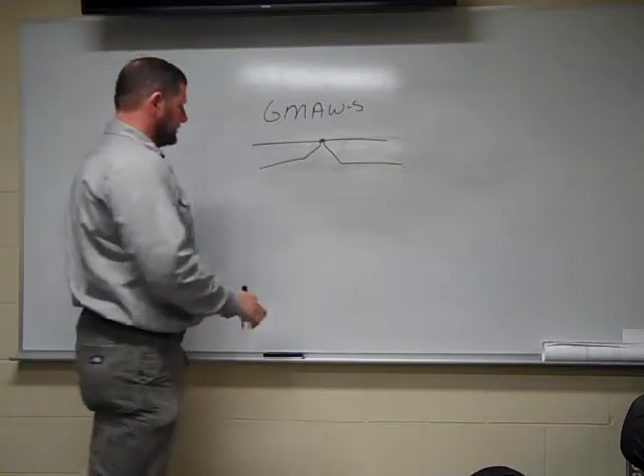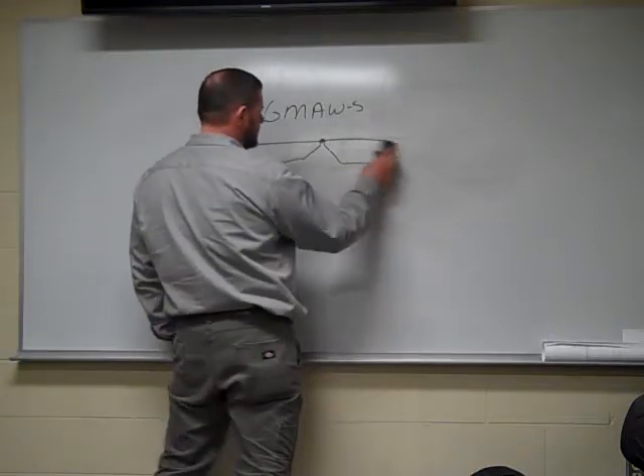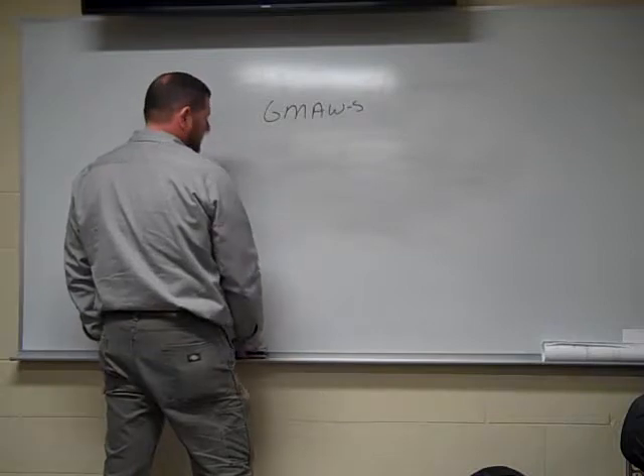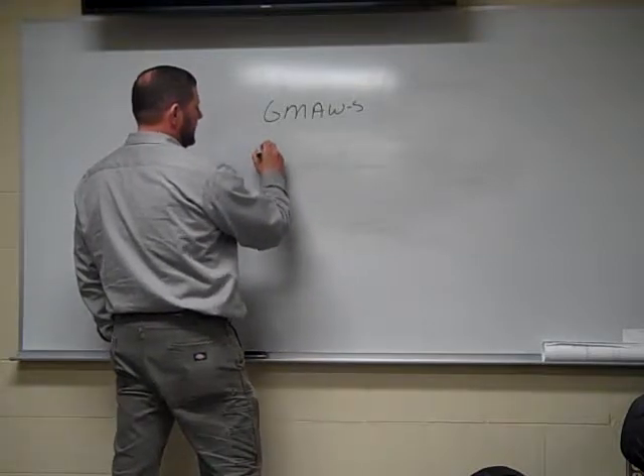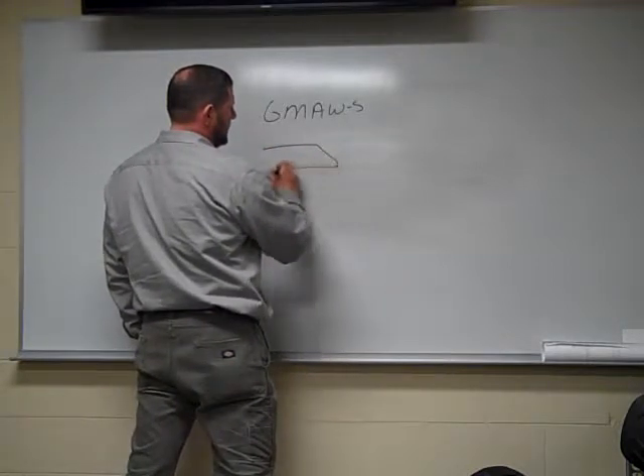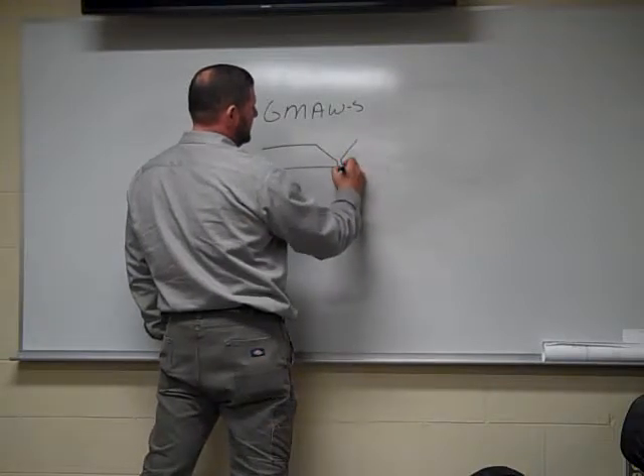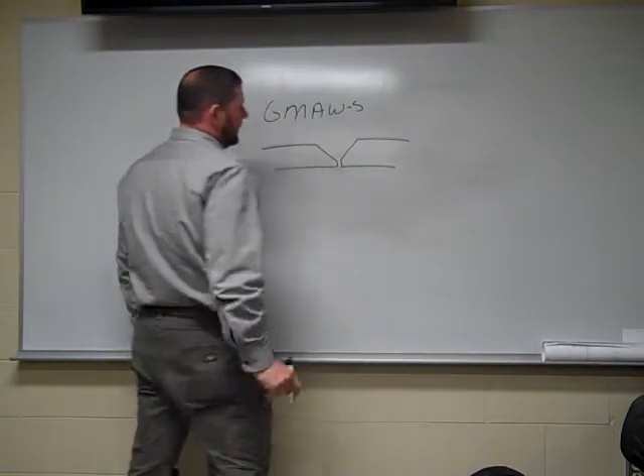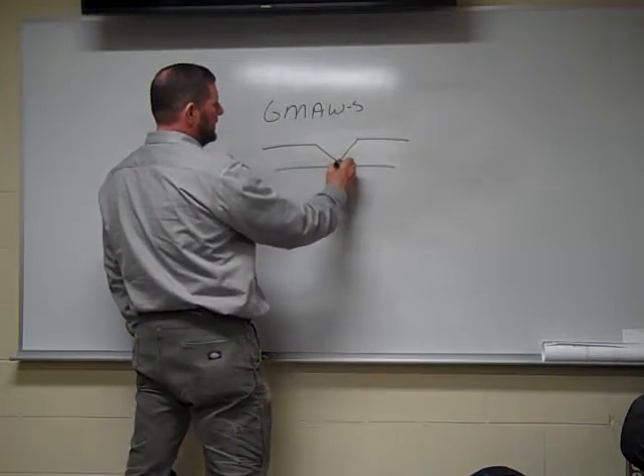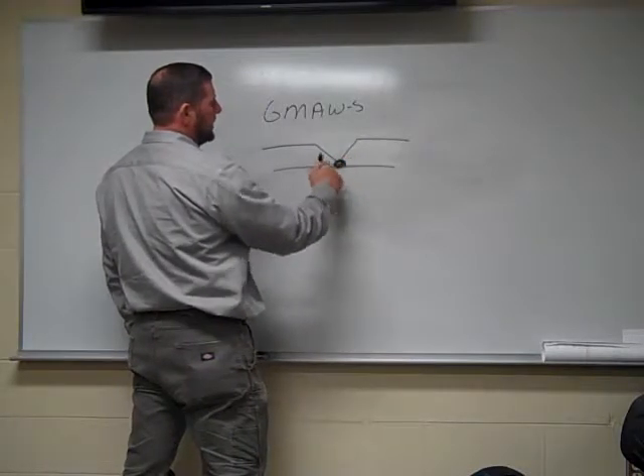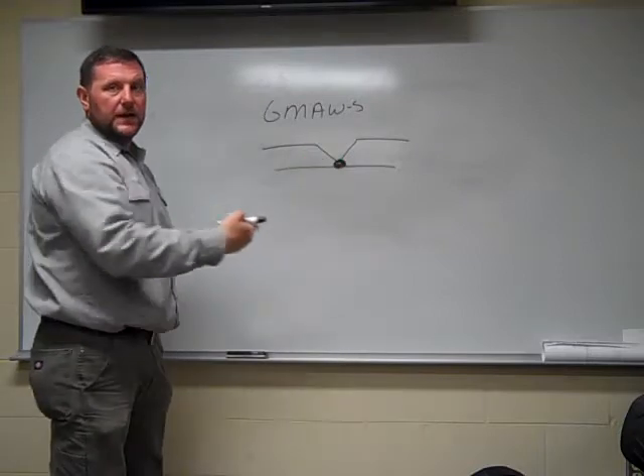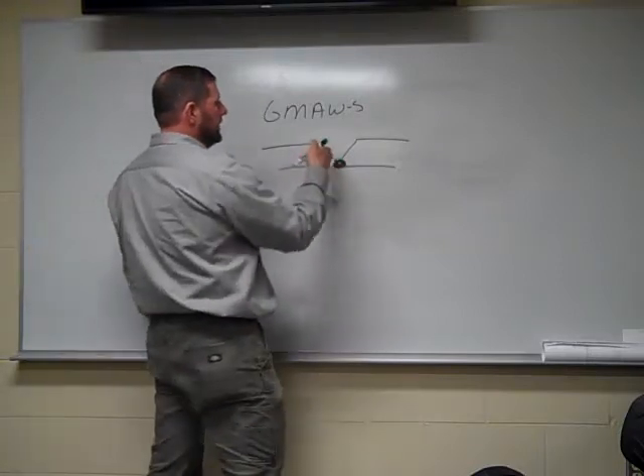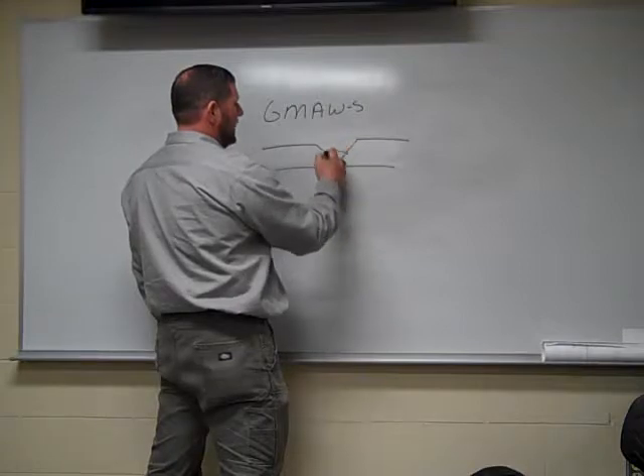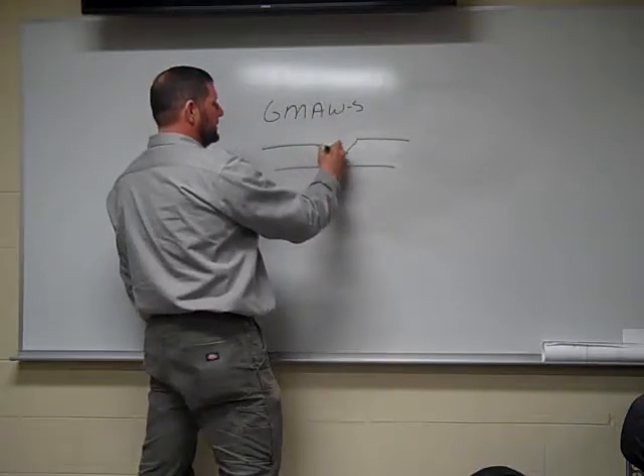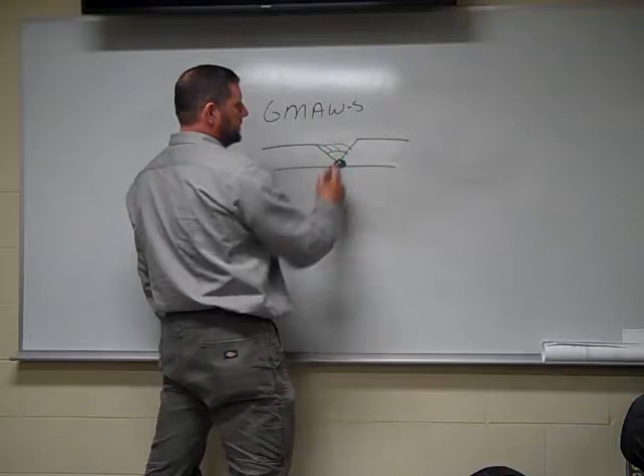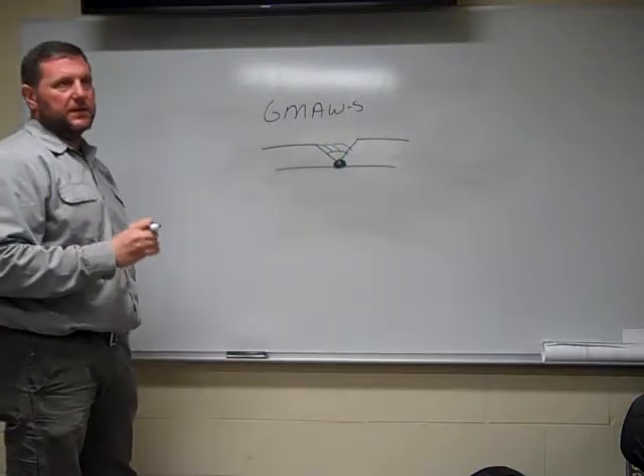As you're welding this V groove, it's very critical that you clean between passes. Very critical. If you need help with this too, make sure you contact your instructor. So what do I mean? So I put my first pass in here, got a little melt through. I'm going to take a wire wheel or a grinder if there's bumps and stuff, clean that pass out, put my next pass in, clean it, put my next pass in, clean it. So after each pass, I'm cleaning it very thoroughly.